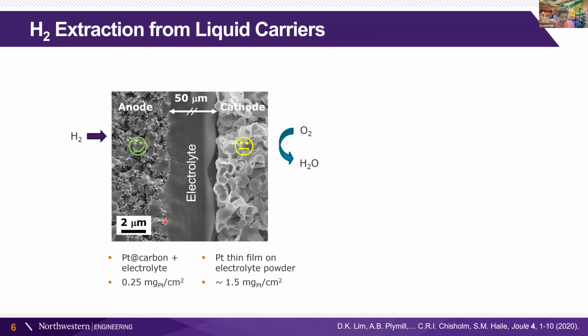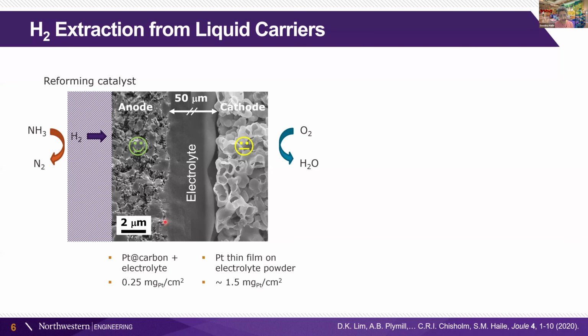Another technology that we've exploited with these electrochemical devices is to employ hydrogen extraction from liquid carriers. And what this does for us is that means that we are able to, like I said, do interesting things with the anode side. And an excellent liquid carrier of hydrogen is ammonia. And it is a good carrier because the product is just nitrogen. There's no CO2 that would need to be recycled. And so we introduce a reforming catalyst, very similar to what we did with our direct methanol and direct alcohol fuel cells.